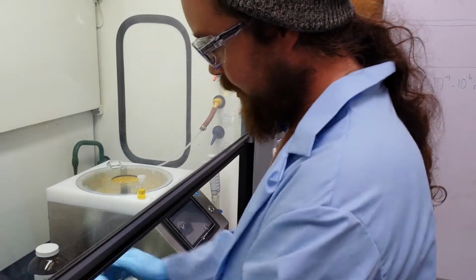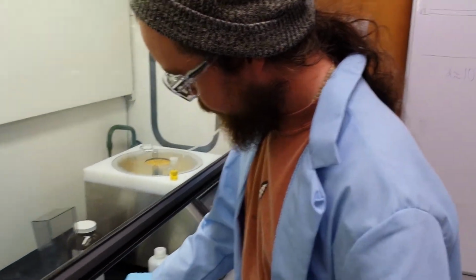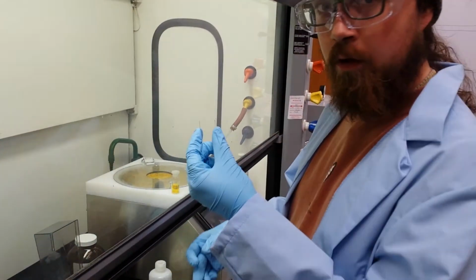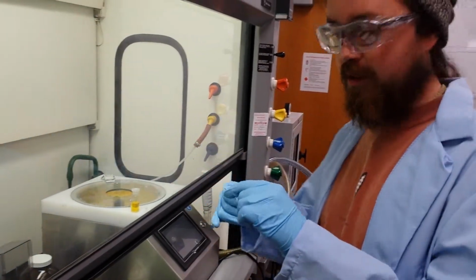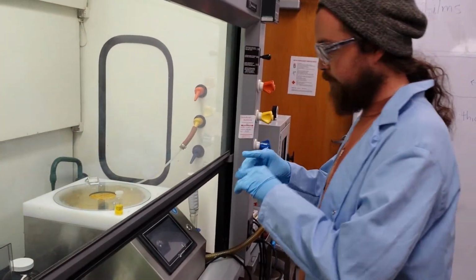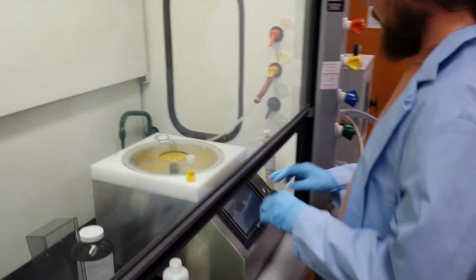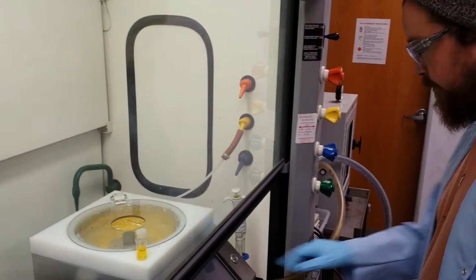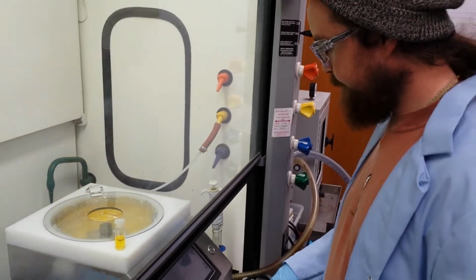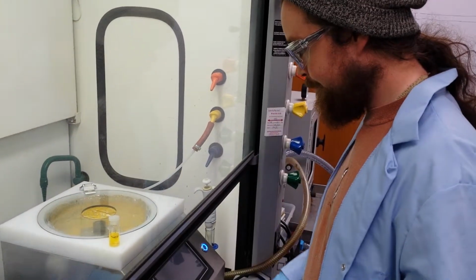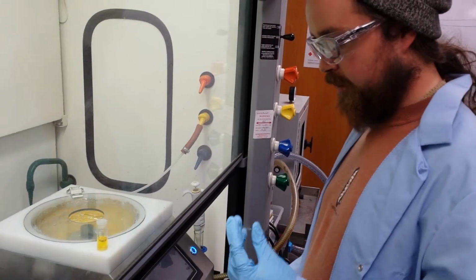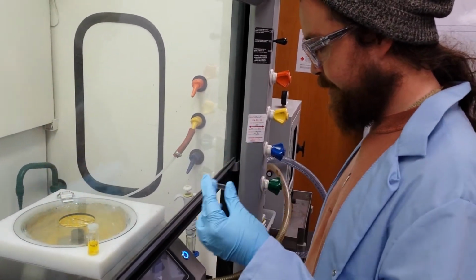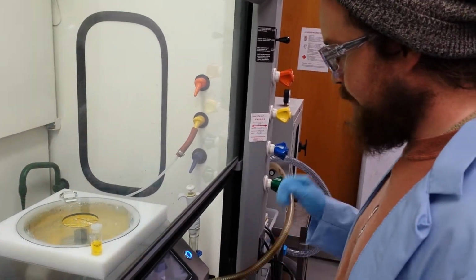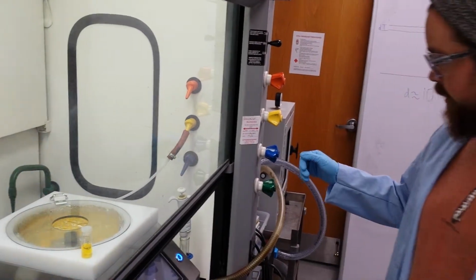So what we do is we take a clear glass substrate. We use microscope slides and cut them into thirds so that they're 1 inch square, and we come over here onto the spin coater, and I'm going to turn it on, and then we're going to secure our substrate into the spin coater by use of a vacuum. And the vacuum is actually going to be here on this knob. It's connected to the spin coater.